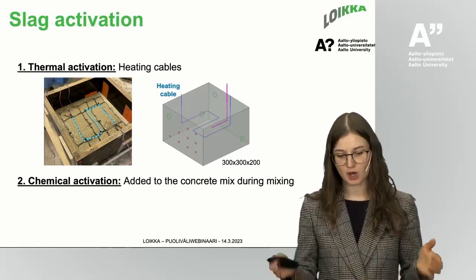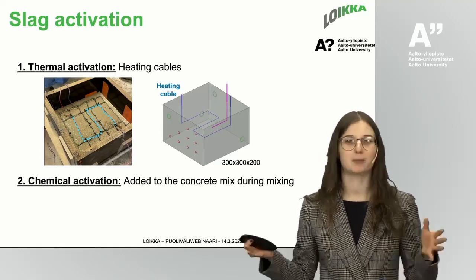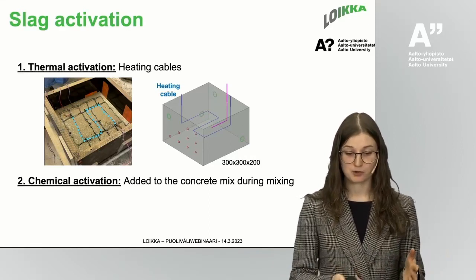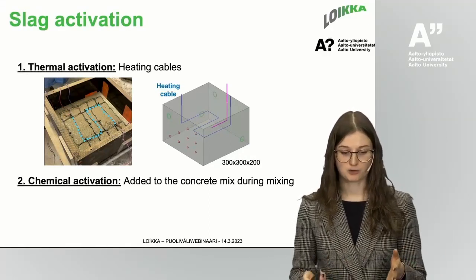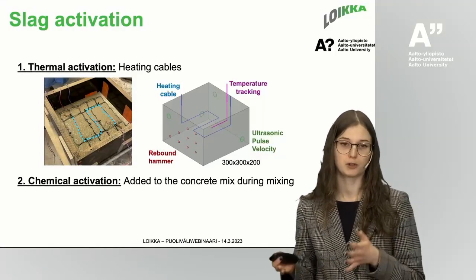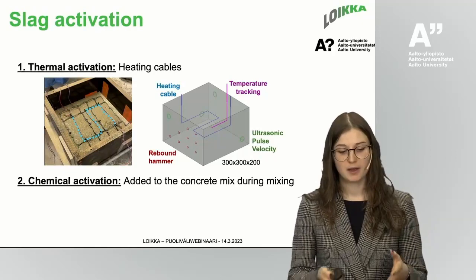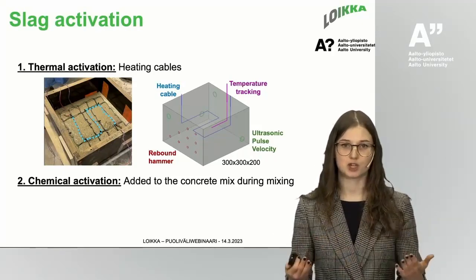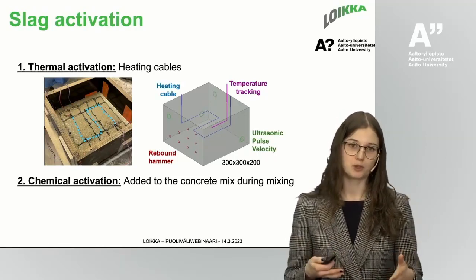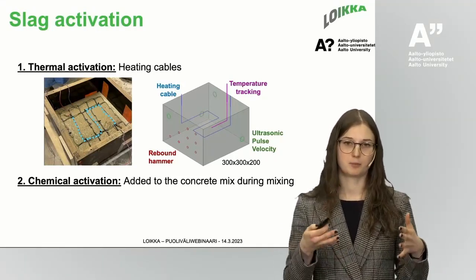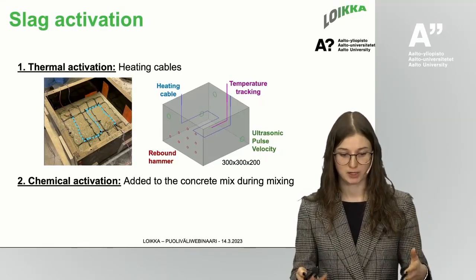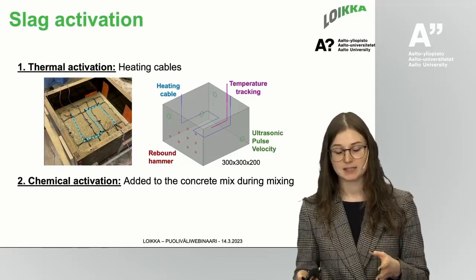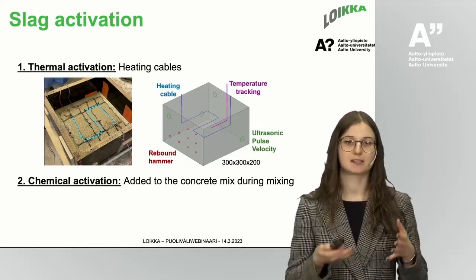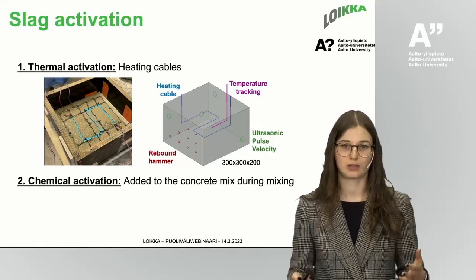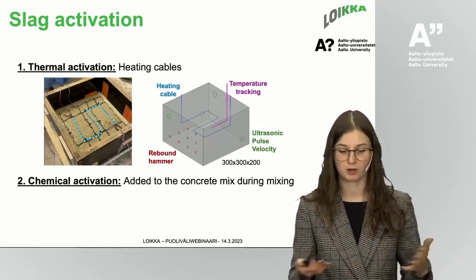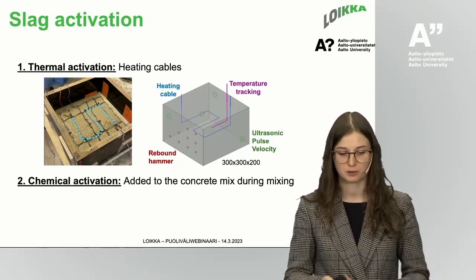Since the size of those samples is pretty large, we cannot put them in a compression machine. So the measuring methods that we use here are non-destructive and include rebound hammer and ultrasonic pulse velocity. With the rebound hammer, we characterize the surface condition of the material, while the ultrasonic pulse velocity allows us to access the in-depth properties of the concrete. Temperature tracking was also implemented to see how the heat is increasing the temperature of the concrete. Is it going too high or not too high? Can we increase the amount of power we're giving to the material?